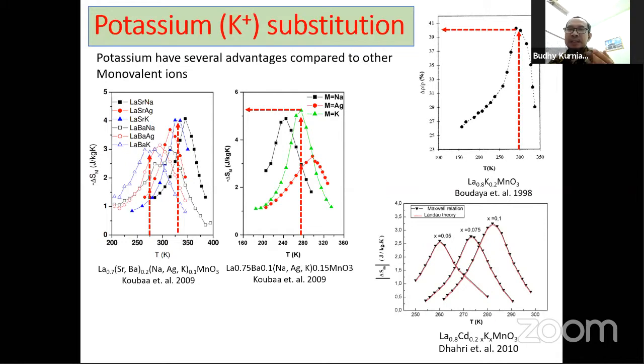So in this material, we try to substitute potassium as the monovalent ion for the sample. In the figure, we have many of the monovalent ions, sodium, silver, potassium, and we see in the curve of minus delta entropy, the highest value among the substitutions is produced by the potassium substitution in this sample. And also, some researchers also found these properties. So based on this information, we try to make potassium substitution in our sample. Next, please.